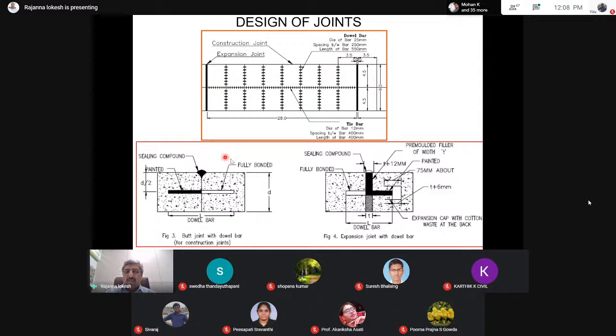This is a similar schematic diagram showing the type of joint, where you can see half portion of dowel bar is painted and other half is unpainted. Each length of dowel bar shall be extended on both the sides for one panel as well as for another panel. On top of the existing groove, we are supposed to go with the sealant compound. When it comes to expansion joint, generally it will be around 20 mm thickness. You can see a filler board will be provided. For the expansion joint, we are going to have an expansion cap, which will allow the pavement to have the movement. Here also, we are going to fill the joint with polyethylene or joint sealing compound.